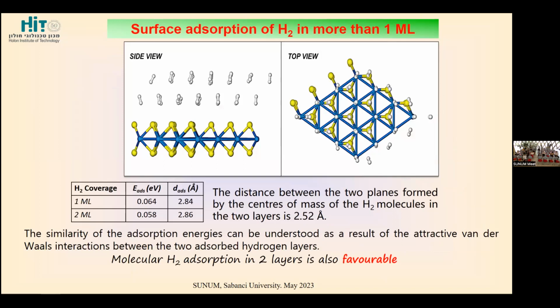The first one: hydrogen can be adsorbed in more than one monolayer, which is quite beneficial for hydrogen release, because we don't want just to adsorb hydrogen. If we would like to use it, then we have to easily release it. And indeed, the calculation showed that hydrogen can be adsorbed in 2 or even more than 3 or 4 layers. It's quite stable at room temperature, and the energy of its adsorption is still quite low, but positive. So this is indeed the case when hydrogen molecules are on top in a number of layers. But it's still not enough.